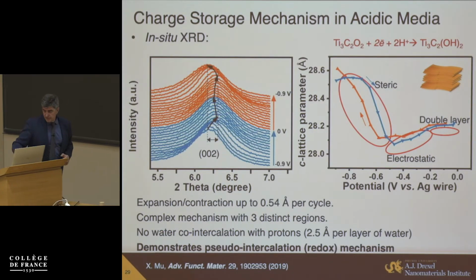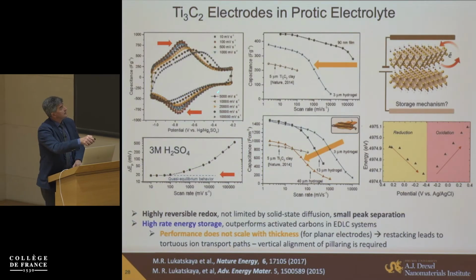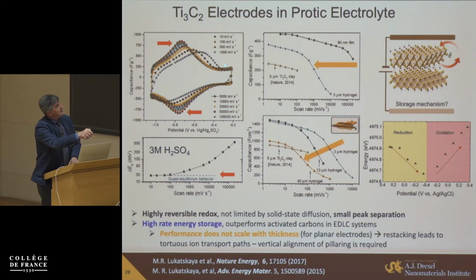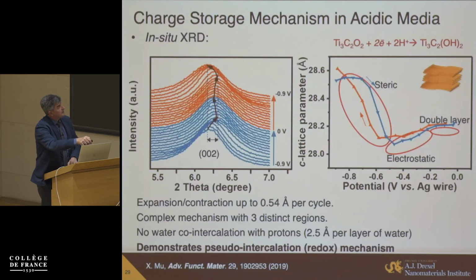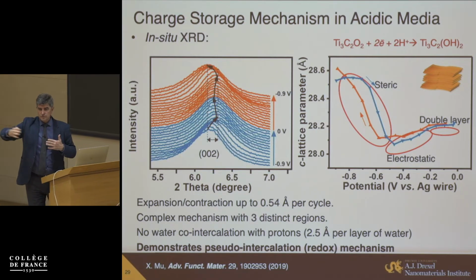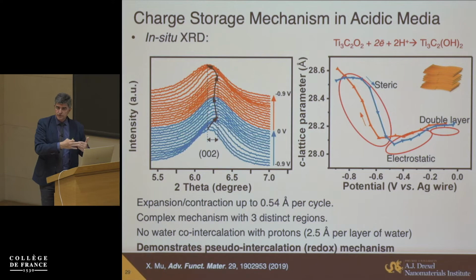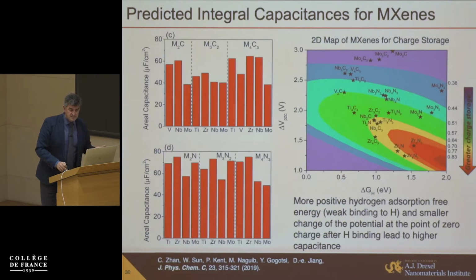You remember the initial part of the spectrum, let me just go back for a second, when there is this really rectangular behavior, XRD shows no changes. There is some electrostatic contraction when more protons intercalate. And then there is this increase. And it seems to be very large here, but in fact it's half an angstrom. And this is exactly the length of the OH-oxygen bond. So you basically switch between oxygen and OH termination, increasing the bond length, increasing spacing somewhat between the layers. So we try to understand this behavior.